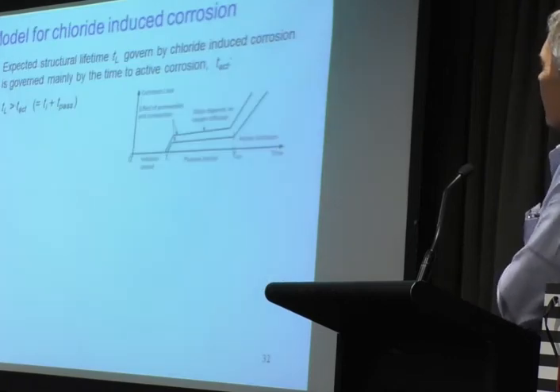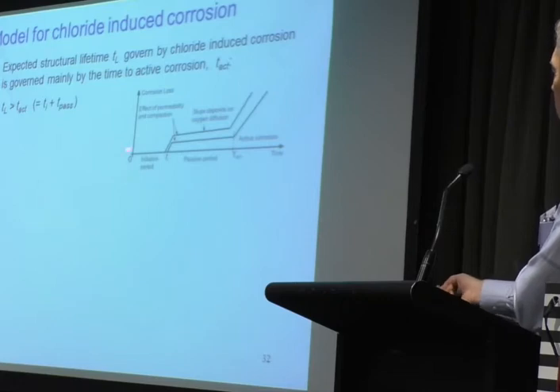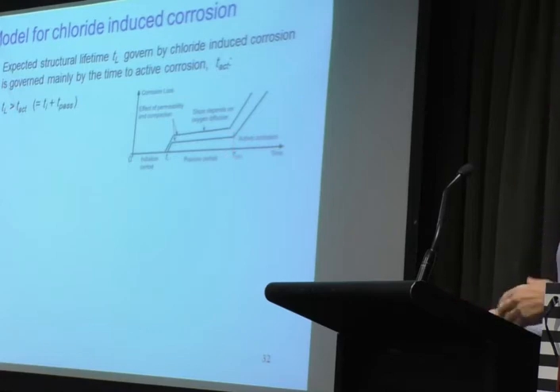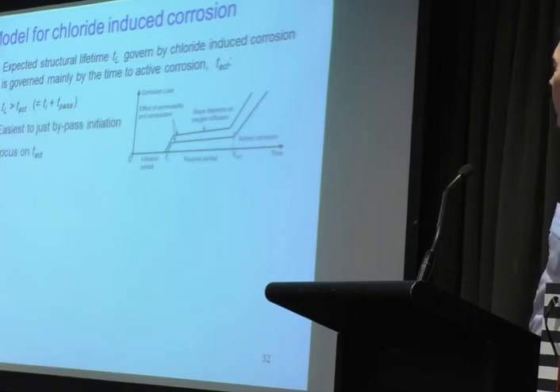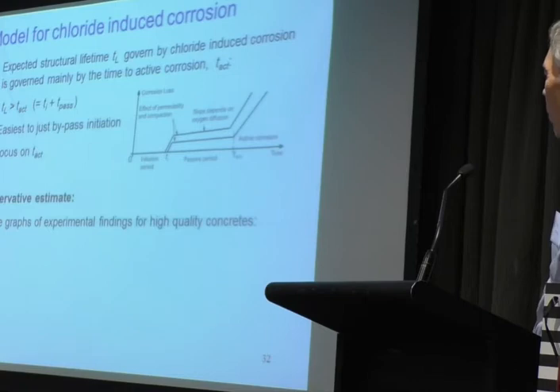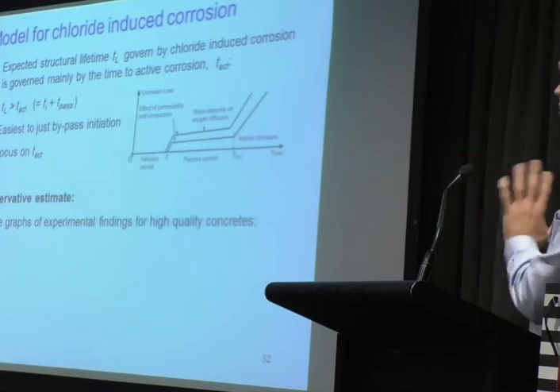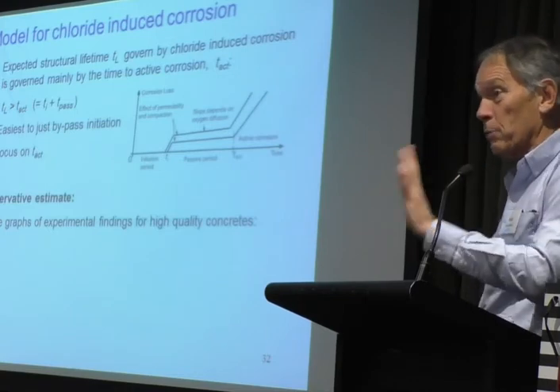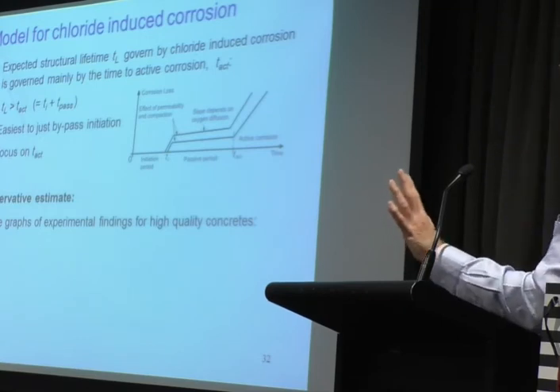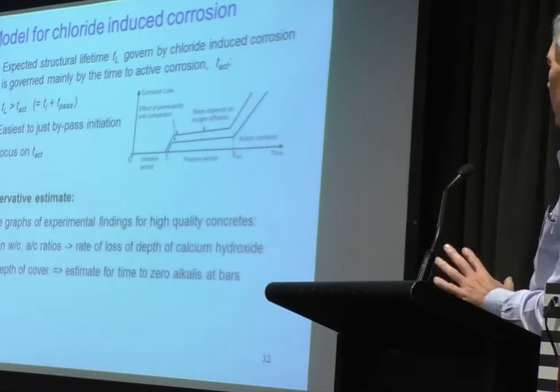Okay, how do we then think about lifetime prediction? Really, we don't care about this bit. We care about that time here. And that time now, in my view, is governed by dissolution of the alkalis in the end. And that's sped up by chlorides. So we just need to focus on that bit. Now, we can use the results we've got so far, and they're for completely uncracked specimens, and I keep reminding you of that. We can use that to make an estimate.